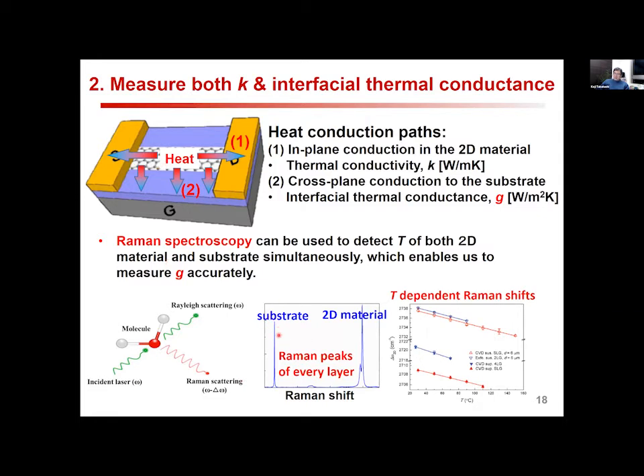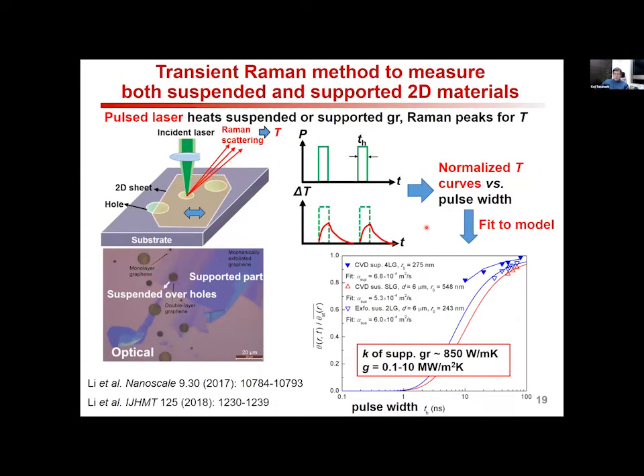This Raman shift is from the substrate. This one is from the 2D material, graphene and so on. This Raman shift is dependent on the temperature, which means from these two signals, we can obtain the two temperatures here and here simultaneously. So we can obtain the interfacial thermal conductance. This is a very excellent measurement method. Based on this principle, we developed the so-called transient Raman method to measure both suspended and supported 2D material.